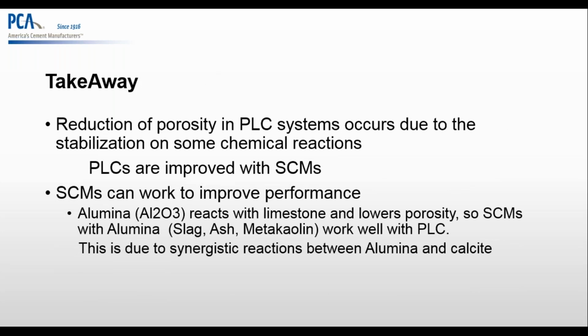So a few takeaways. Reduction of porosity in a PLC system occurs due to the stabilization of some chemical reactions, like I said. The calcium carboaluminate works well, and that's in the reaction with the slag and the limestone; those synergies work very well. Overall, of course, the PLCs are improved with SCMs. Like I said, aluminas react very well with limestone. That's where the chemistry happens. It lowers the porosity. So using SCMs in your mix design is